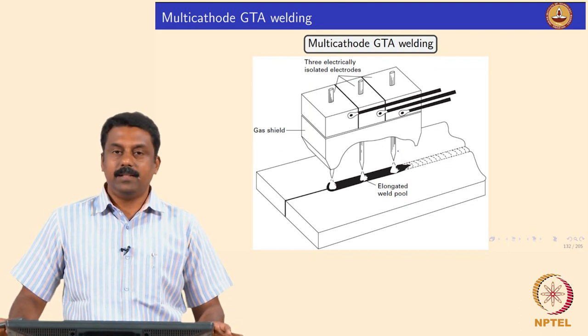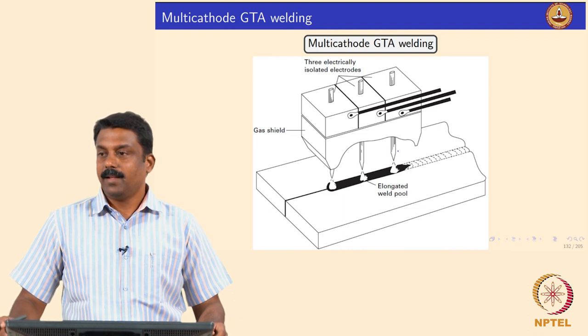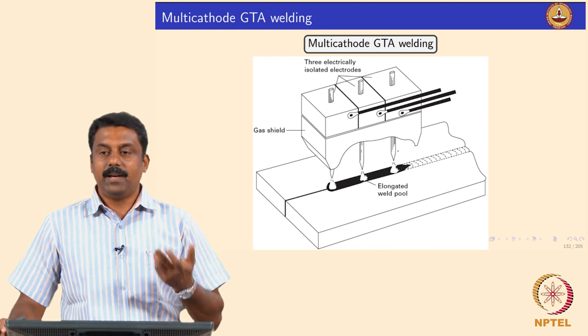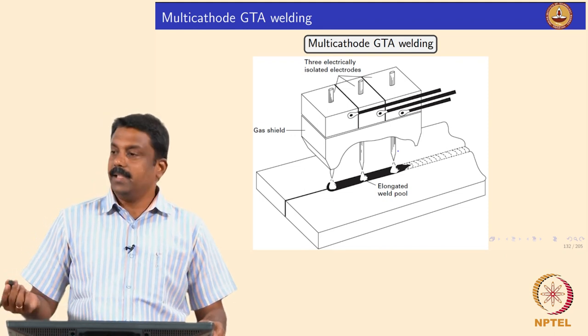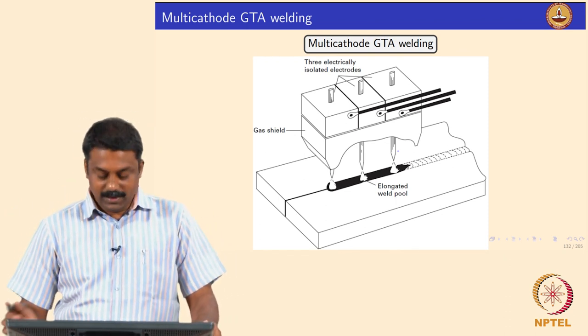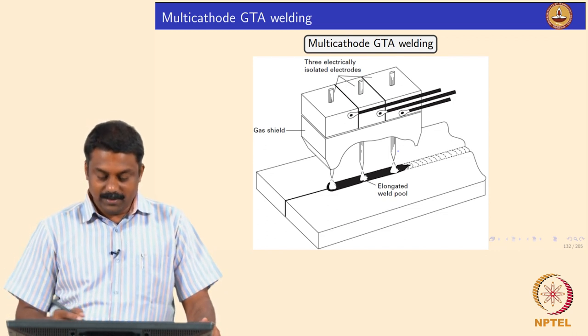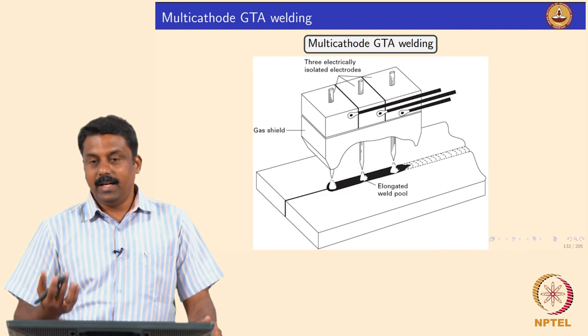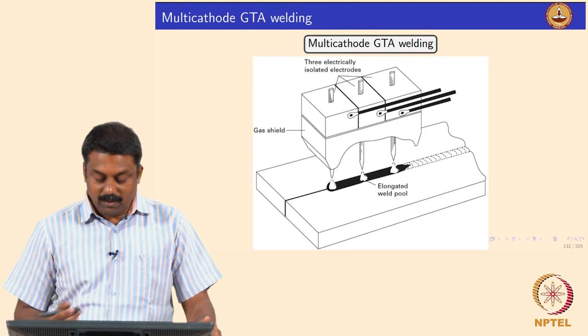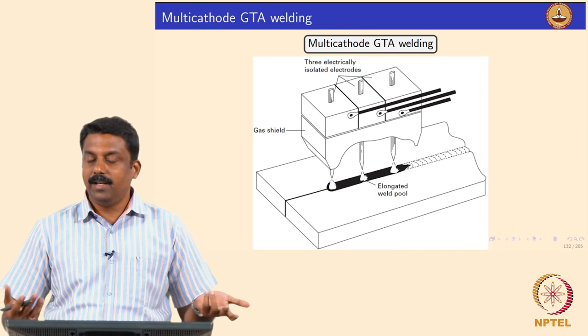Sometimes if you have a very high energy density process you always have an undercut — that means penetration may not be achieved if you do not have a keyhole. In those applications we can use a multi-cathode TIG process. In this case we melt more, basically, so if you want to increase productivity we can use instead of one tungsten electrode — because we are always greedy — and you can also avoid the undercut by melting more volume so the liquid can flow and fill the weld cavity.